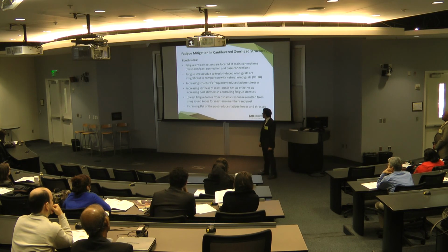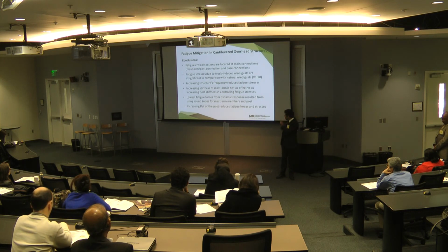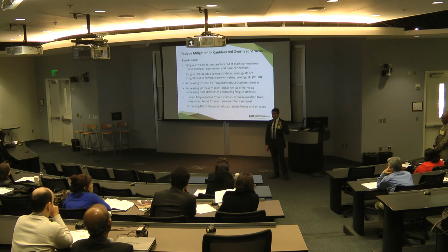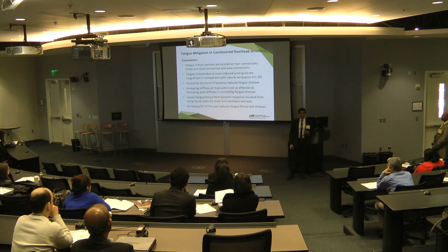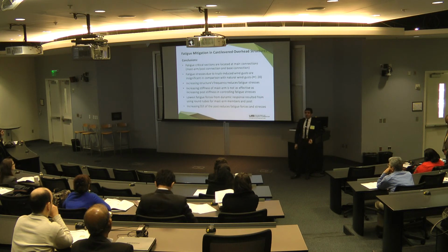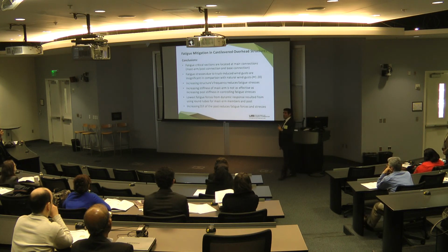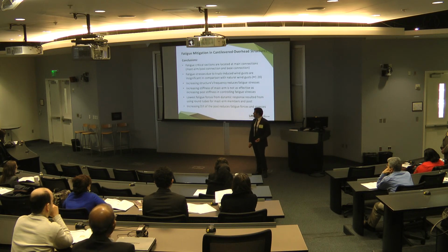The conclusion: the critical section of fatigue, based on the literature review, was located at critical connections, the connection between post and horizontal arm and the base of the post. Second, fatigue stresses due to truck-induced wind gust are not as significant as natural wind gusts. Increasing structure frequencies reduces fatigue stresses. Changing the stiffness of the mast arm is not as significant as changing the stiffness of the post. And as we said, as we increase the D over T for the post, we decrease fatigue stresses.